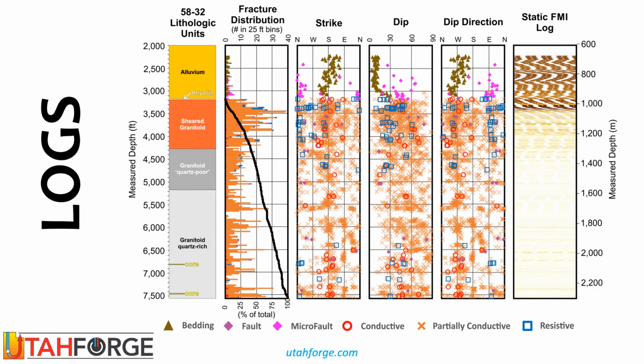Physical logs were obtained by tools that were run in and out of the hole before the casing pipe was installed. This is an example of a micro-resistivity log. This particular tool has pads that are on springs that go out, touch the borehole walls, and measure how resistive they are. This log from well 58-32 goes through the alluvium, into the sheared granite, then down into the different flavors of granite. In the static image log, we see dark colors which indicate that it's conductive. So in the basin fill, there are pore spaces between the clasts full of conductive salty fluid.